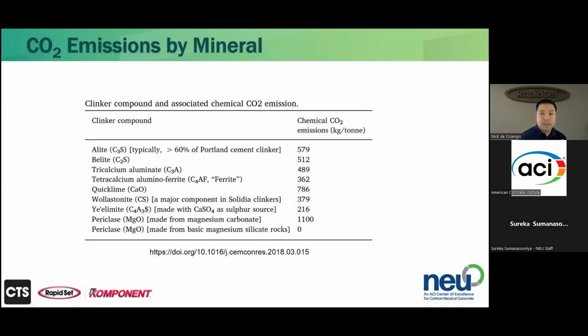This chart is from a 2018 study looking into the chemical CO2 emissions for each clinker compound, and you'll see at the top of the list that alite and Belite are there, and they're both rather heavy contributors to chemical emissions - 579 kilograms per ton of alite produced, 512 kilograms of carbon for every metric ton of Belite produced. And then if you go down - it was on the slide, I didn't mention it earlier - but third from the bottom, yeelimite, that's the mineralogical name for CSA cement.